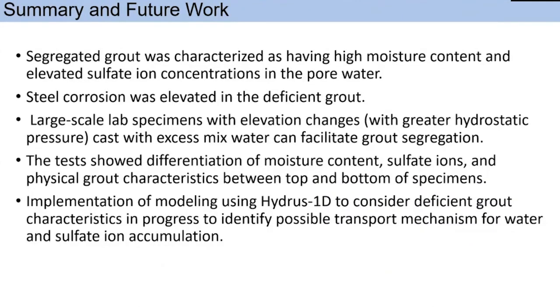This is the summary and future work of this project. Segregated grout has high moisture content and elevated sulfate ion concentration in the pore water. Due to this, steel corrosion was elevated. This can facilitate grout deficiency by differentiation in moisture from upper and lower elevation, where tests show differentiation of moisture content, sulfate ions, and physical grout characteristics. Implementation of modeling using Hydrus 1D to consider deficient grout characteristics is in progress to identify the transport mechanism.